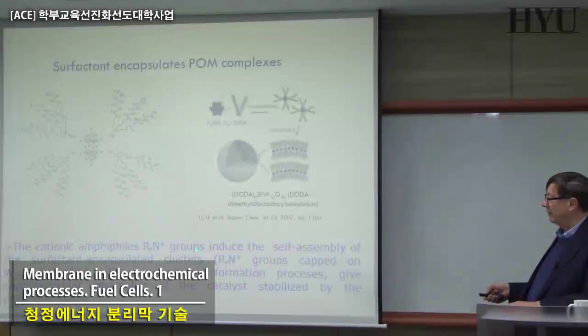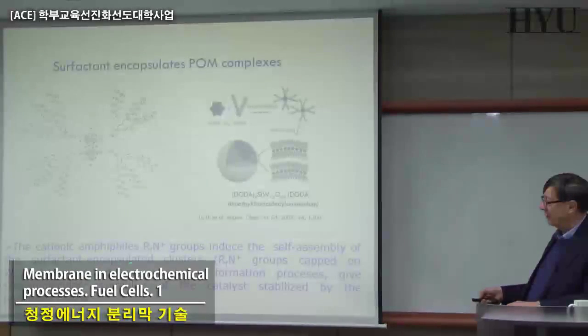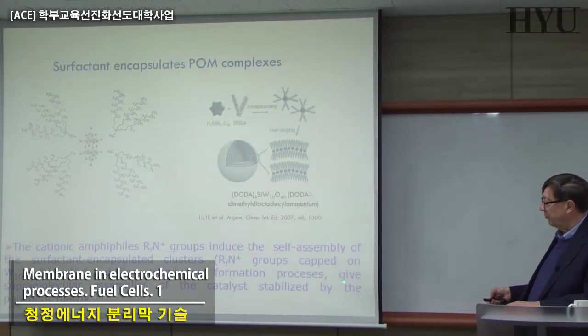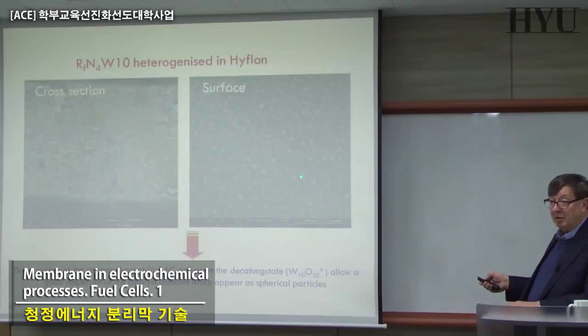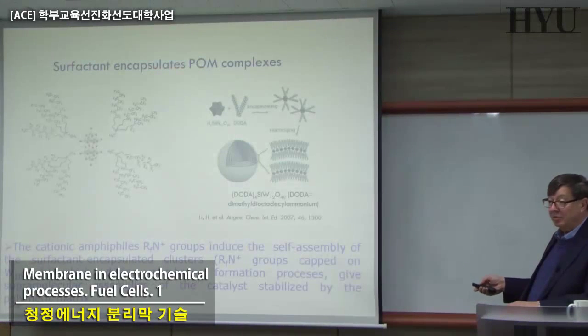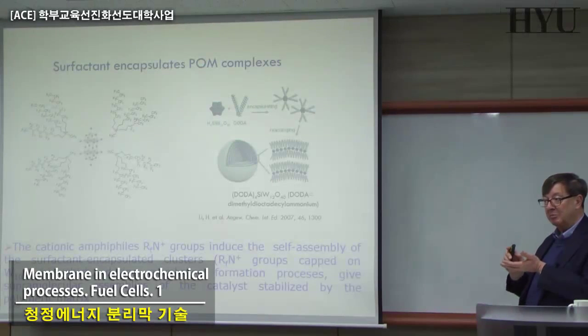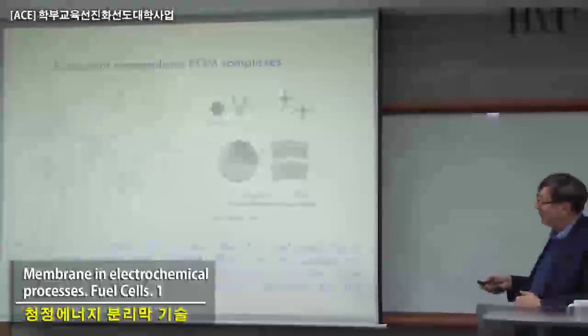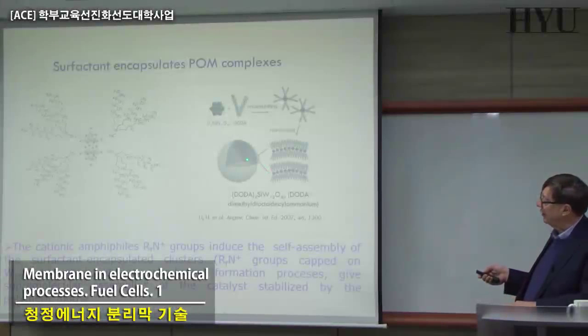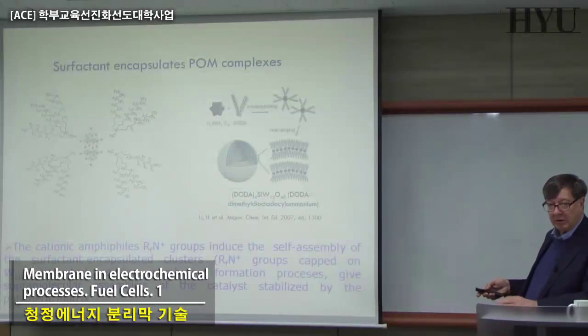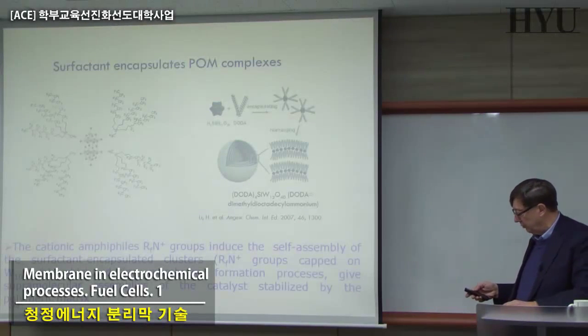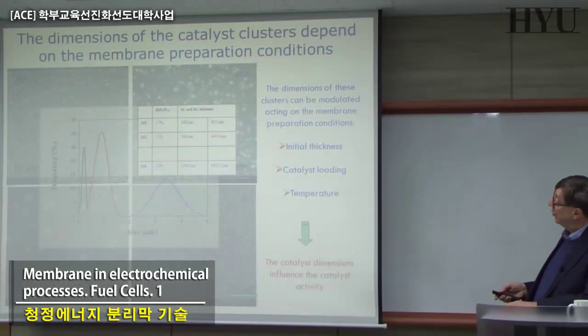This cationic amphiphilic group, this R4N+, induces the self-assembly of the surfactant-encapsulated clusters, which during membrane formation give a supramolecular assembly to the catalyst stabilized by the polymeric matrix. So all these nice droplets that you see here were nothing more than this kind of system. That means the system has reorganized itself, forming droplets in which your catalyst is blocked inside. So that's quite ideal. That is a very good reproduction of what nature is doing.